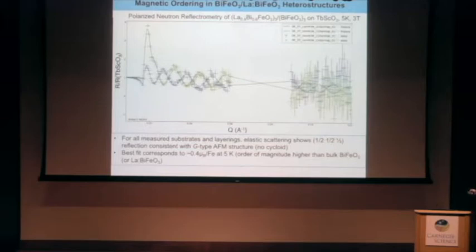So in this case, this looks really impressive because this splitting should all come from magnetization, but I should warn you that terbium scandate has a really large anisotropic paramagnetism, and we couple to that too. So a large portion of this spin asymmetry is coming from the magnetization in our substrate, but because we have depth profiling, the Q dependence and where we deviate gives us the ability to tell apart the magnetization in the substrate from the magnetization in the film as we fit our model iteratively.